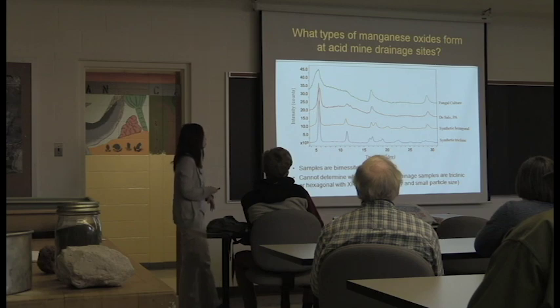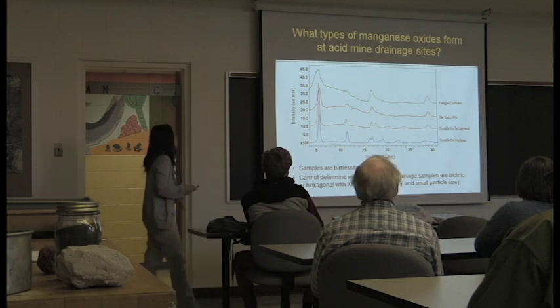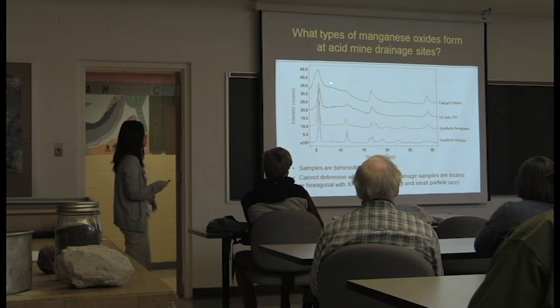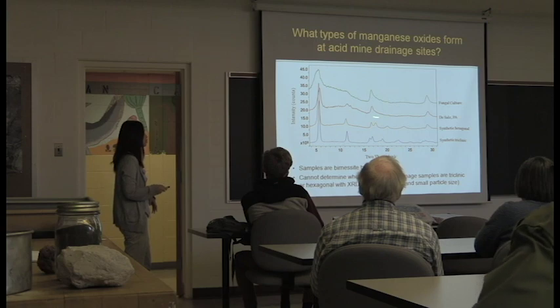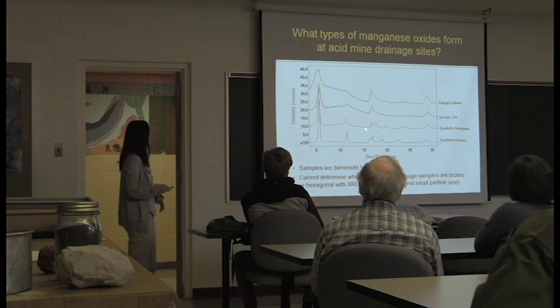The differences between the synthetic hexagonal and synthetic triclinic can be seen in this 15 to 22 degrees 2 theta region, where you have different numbers of peaks and different peak positions. Above that are 2 natural samples, and they both are birnessite because they have this peak right here. But when we look at this 15 to 22 2 theta region, we see some really broad peaks, and we can't really tell if they're hexagonal or triclinic.